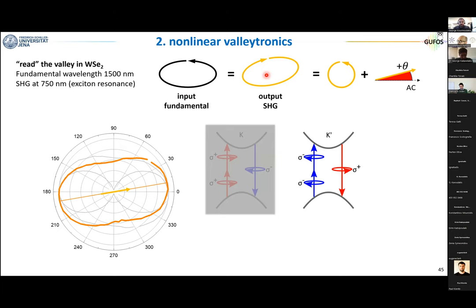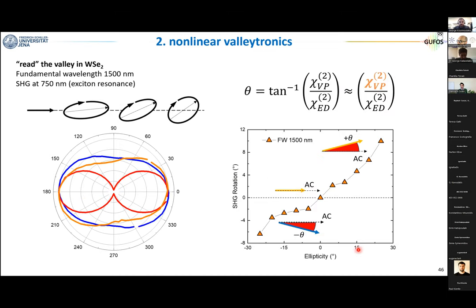Now imagine that you do these experiments for different values of the ellipticity. This is the zero line, no rotation. We enter linear, the output is linear. But you can clearly see that as you change the ellipticity, you can go to positive or negative values of second harmonic rotation. And if you do some algebra, it turns out that this angle theta is directly proportional to the ratio between the valley polarization and the intrinsic electric dipole nonlinear response.